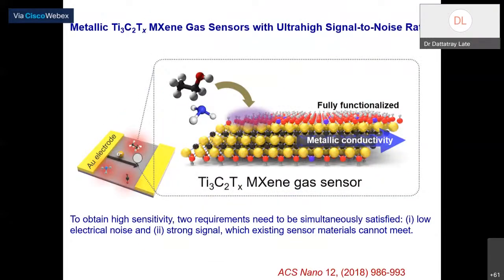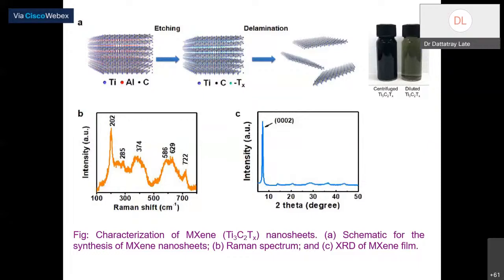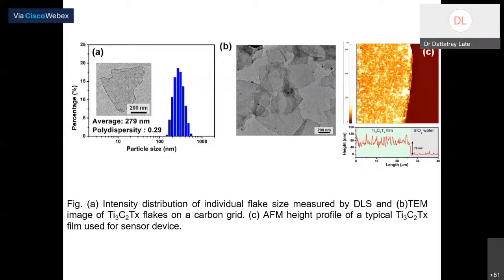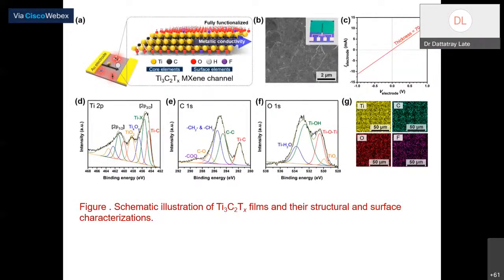And this is another material. We have titanium carbide MXene as a function of gas sensing application. Of course, you can characterize by various techniques like Raman spectroscopy, XRD, and all these things. You can synthesize just by liquid exfoliation, micromechanical exfoliation, and many other synthesis methods can be used. Of course, you can characterize by Raman spectroscopy, TEM, AFM, and lot more. Of course, you can do XPS analysis to find out the exact concentration of this particular material and all, right?